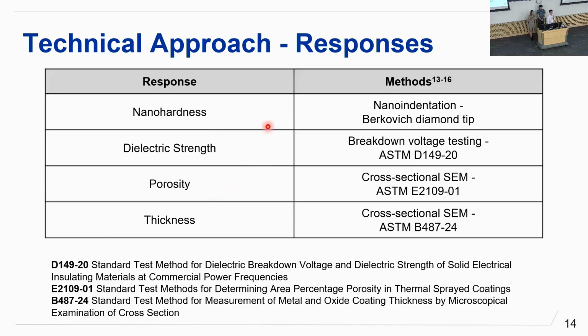So our responses that Connor kind of laid the foundation on. So to test nano hardness, we decided to do nano indentation through INL using a Berkovich diamond tip. Secondly, we tested the dielectric strength of the material using breakdown voltage testing to the ASTM standard of D149-20. Thirdly, we tested the porosity of each spray or each experiment with a cross-sectional SEM image to the ASTM standard of E2109-01. And finally, we tested the variation in thickness with the same cross-sectional SEM to the ASTM standard of B487-24.